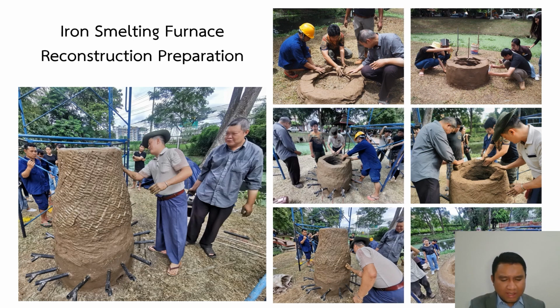Next step is the smelting furnace. We try to create the same model as much as possible according to the ancient assumption. Clay is used for making the smelting furnace structure. The width of the furnace base is 100 cm. The height is 140 cm. The furnace mouth is 80 cm wide, and the thickness of the furnace wall is 20 cm.